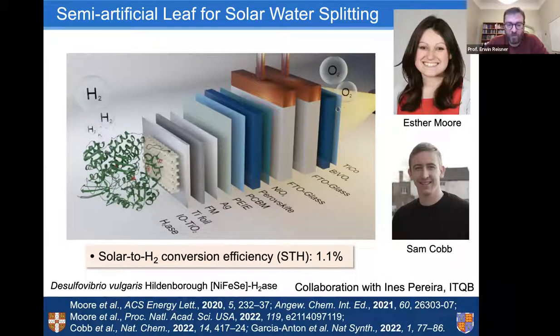Okay, so we were thinking next about efficiency. And I've mentioned before, our efficiencies were low, below 1% for syngas generation or CO2 reduction. And this really was because our CO2 reduction catalysts were synthetic catalysts. And even the best catalysts we have employed required a significant overpotential to operate, which means you have to give them a couple of hundred millivolts until they actually start catalysis. And this is work that was started by Esther Moore, and Sam Cobb is working on this now. This was really the idea of integrating redox enzymes, in this case, for example, hydrogenase, or later on I will show CO2 reductases, that can work much more efficiently and do not require this large overpotential.